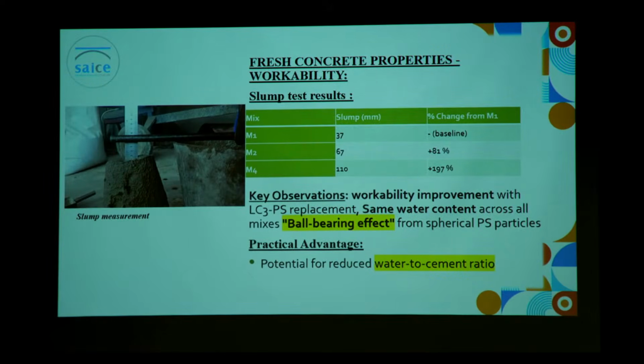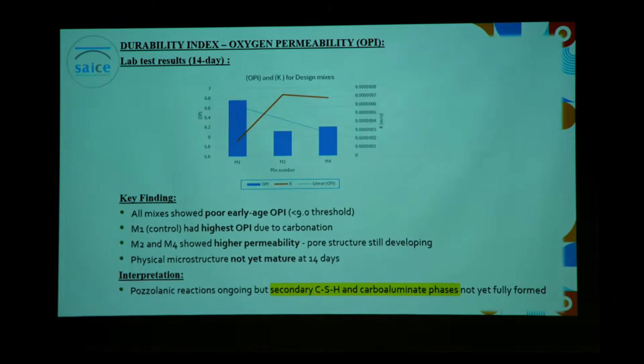For the fresh concrete properties, we witnessed that workability improved as we introduced our replacement levels or our study materials, especially our platinum slag. It improved the workability and flow of our concrete mixture due to that ball bearing effect that I mentioned earlier on, which reduces the friction due to the spherical composition of our platinum slag. And then the practical advantage of having this ball bearing effect would be that our water to cement ratio could then be reduced, potentially using less water within our concrete mixture.